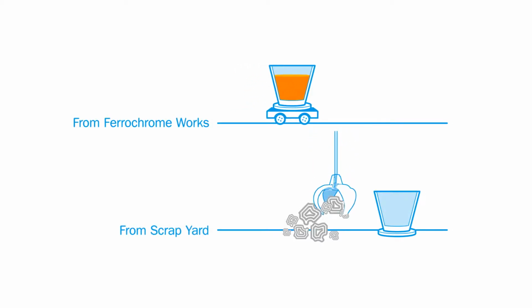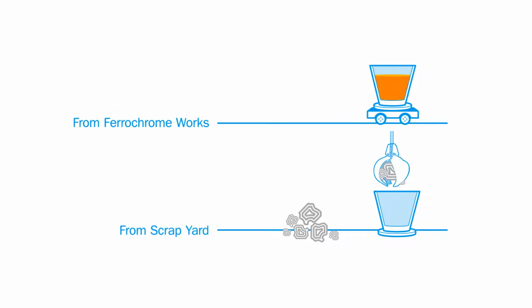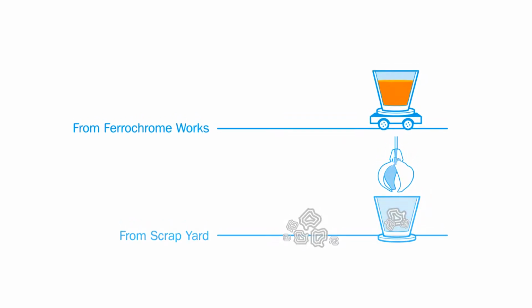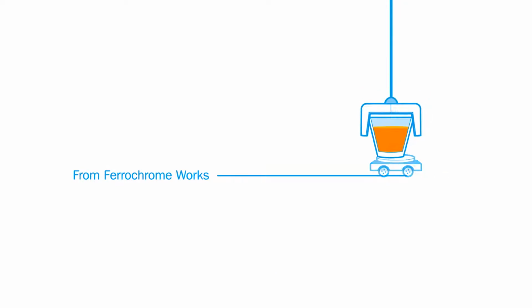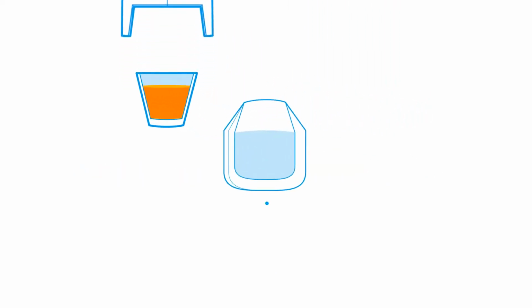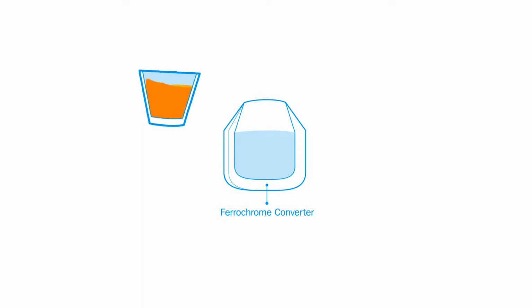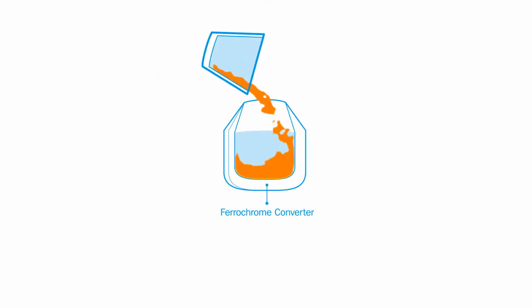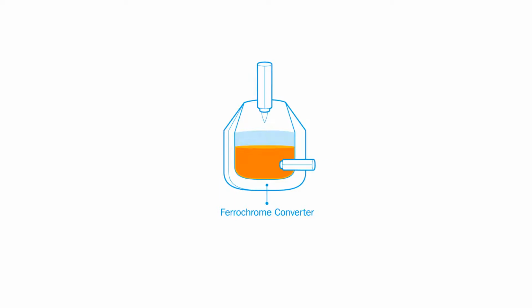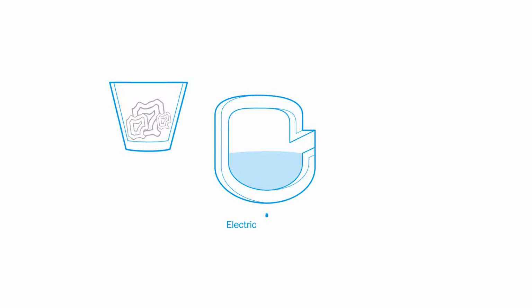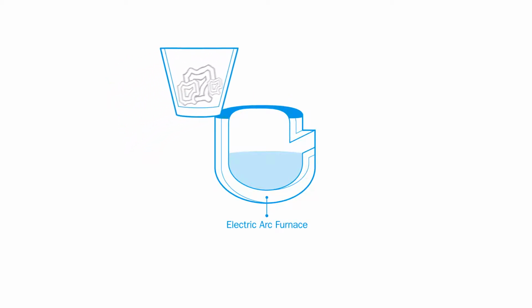Recycled steel, which can account for up to 90% of the raw material used in Outokumpu's stainless steel production process, is dried before melting. Molten ferrochrome, which arrives directly from the ferrochrome works, is poured into a ferrochrome converter, where silicon and some of the carbon is removed from the melt. By using molten ferrochrome in the ferrochrome converter, Outokumpu achieves significant energy savings and an increase in production capacity.